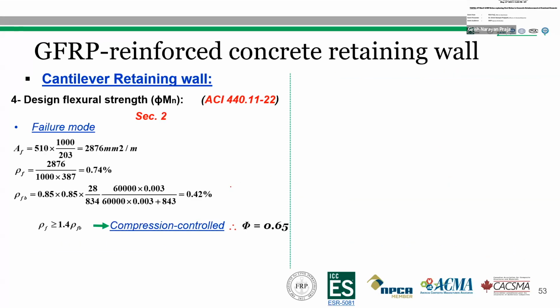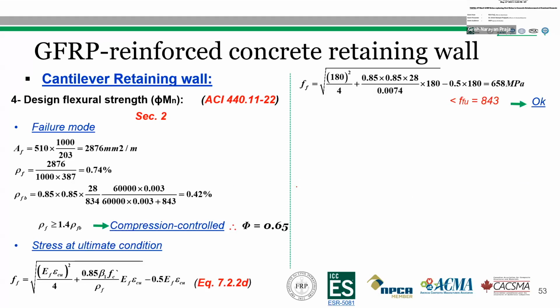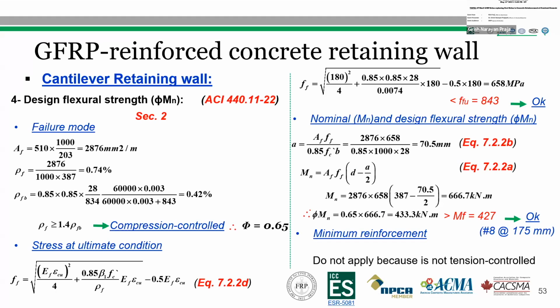The design flexural strength calculation is done for section 2 to show how the moment capacity is calculated for a compression control section, where the provided reinforcement ratio is greater than 1.4 times the balanced reinforcement ratio. And so we have considered a reduction factor of 0.65. The stress in the FRP bar is calculated using this equation and is equal to 658 megapascal, which is lower than the ultimate tensile strength of the GFRP bar. The nominal and the factored design flexural strength is calculated using this equation, where a is the depth of the rectangular concrete stress block. The design flexural strength is greater than what we require, 433 kilonewton meter, which is greater than the 427. And here the minimum reinforcement doesn't apply because the section is compression control.